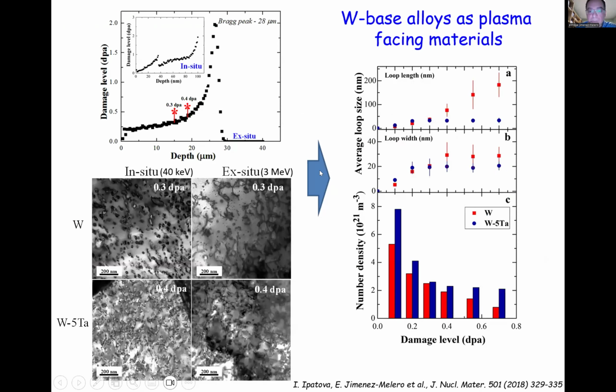Without going into all the details, we can compare doing it in situ with medium energies or ex situ with high energies to avoid surface effects, and then you can count the number density as a function of dpa and the average loop size. You can then see that one of the dimensions doesn't grow, so you don't form those elongated structures that you form in tungsten.